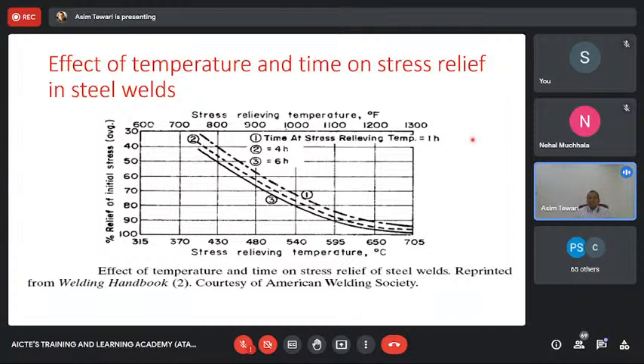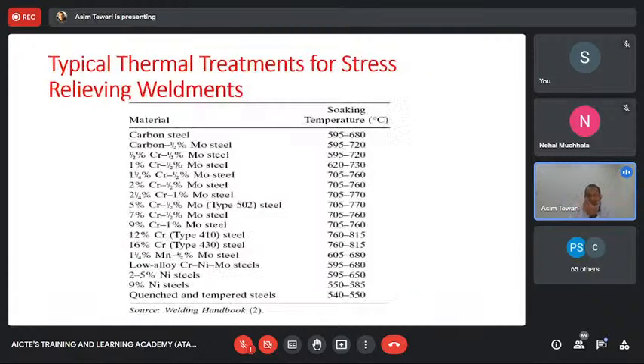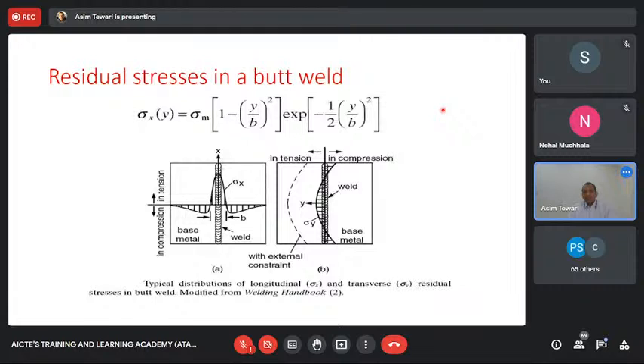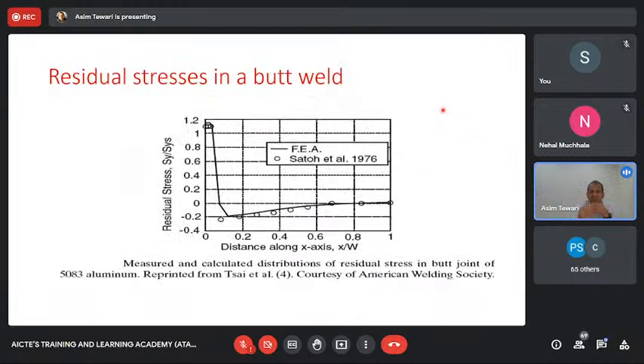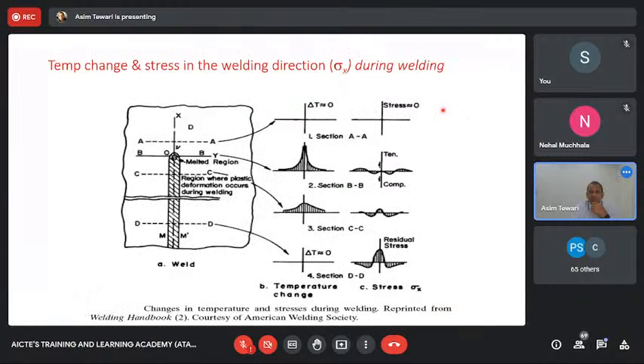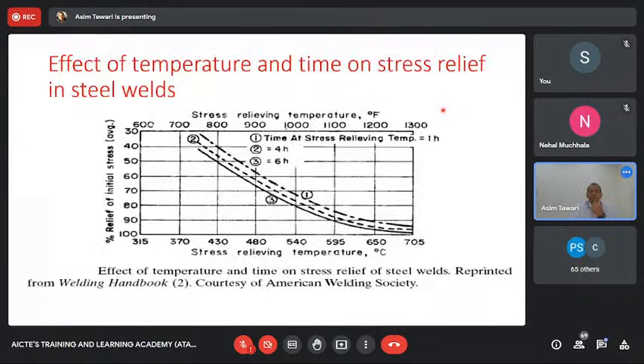And why does this happen? This happens because of many mechanisms. One of them is that heat is provided, and the heating is causing the atoms to move, and the stress goes through a stress relieving process. So the temperature exposure at a long enough time causes the heat to relieve residual stress.